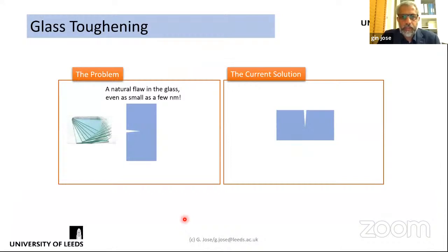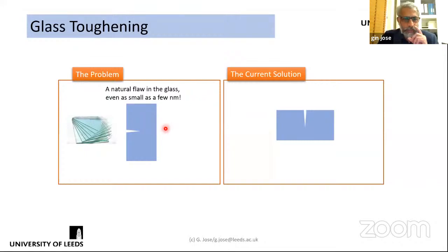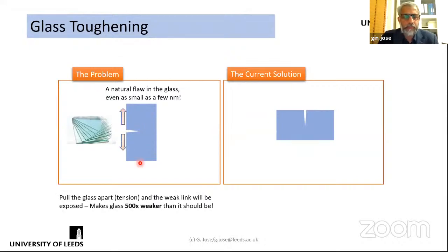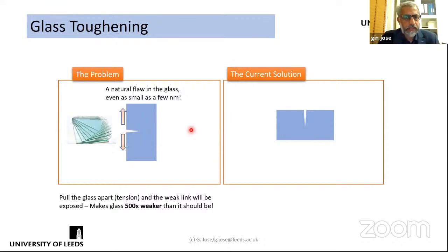The second application is strengthening the glass screens of smartphones. Currently, there's a high chance of the screen cracking when you drop a phone. Glass breakage happens because of micro-cracks — the size and density of these cracks ultimately leads to failure. If you can seal these micro-cracks, you can toughen and strengthen the glass, reducing the chances of breakage on impact.